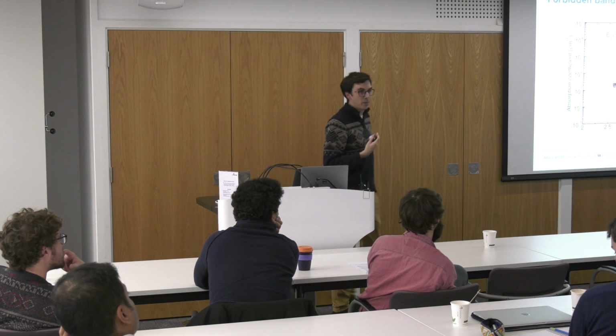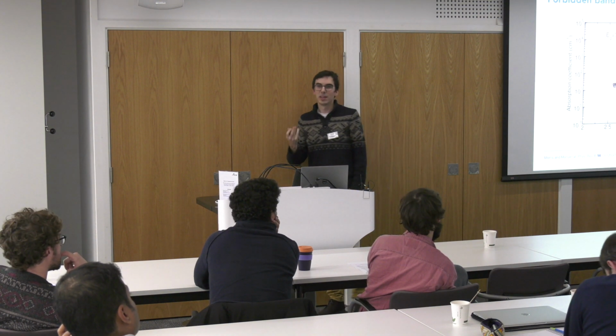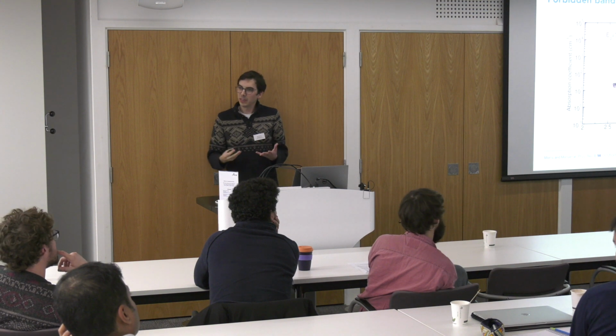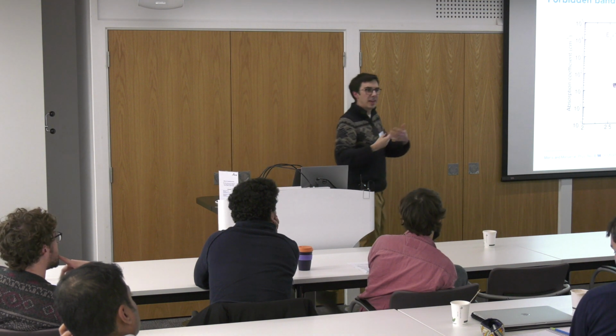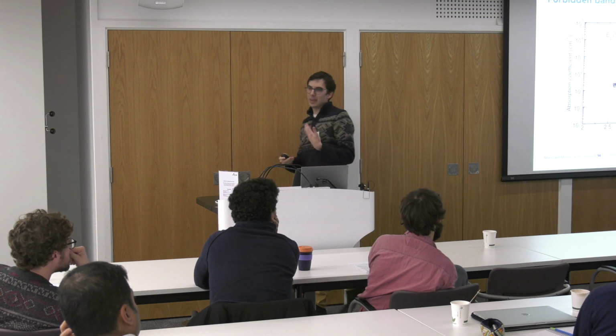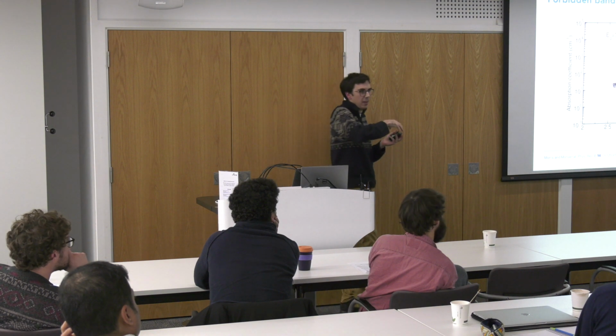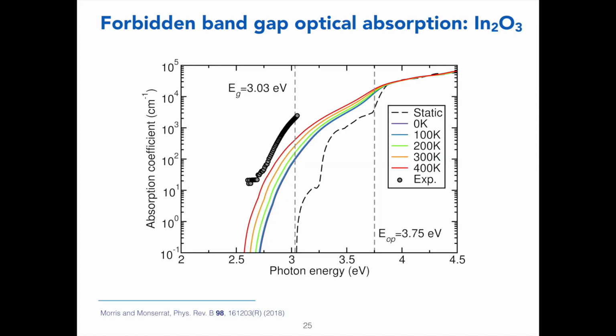So again, this is coming from dynamic disorder. And there are various ways in which you can think about this. A real space picture is that as your atoms vibrate, they dynamically break the inversion symmetry of your system and therefore allow that transition to occur. If you prefer to think of this in terms of perturbation theory, then you have an initial state, an intermediate state of opposite parity that is then allowed, and then a phonon, and the final state of the original parity. So indeed, if we include those dynamic disorder effects, then we find much better agreement with experiment.